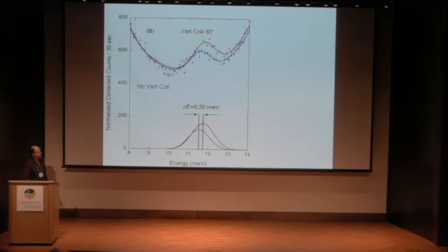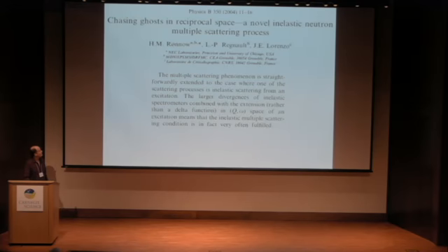Okay? That should not happen with a real mode. All right. Now, there was a paper that appeared in Physica B in 2004 by Henrik Rønnow and collaborators that explained a phenomenon like this in copper germanate, a magnetic system. And they extended the concept of double scattering and multiple scattering, which applies to elastic Bragg scattering, where you can get forbidden half-order Bragg peaks, for instance, from double scattering processes, to the case where one of the scattering processes involves an inelastic cross-section, such as a phonon.